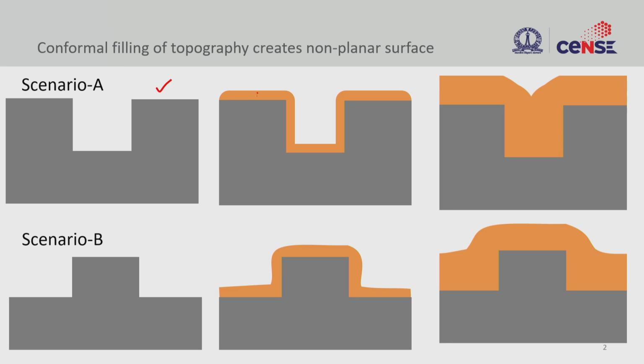What is the meaning of conformal? The vertical and horizontal thickness, let's say h and h dash, should normally be equal. If we have a uniform thickness coating the top, the side wall and the bottom, we call this a conformal deposition. This is good for many applications, but if you want to fill this trench, you normally end up with a topography like this. You won't get a flat surface, and if you want to put circuits on top of this layer, you will transfer whatever topography we have here.